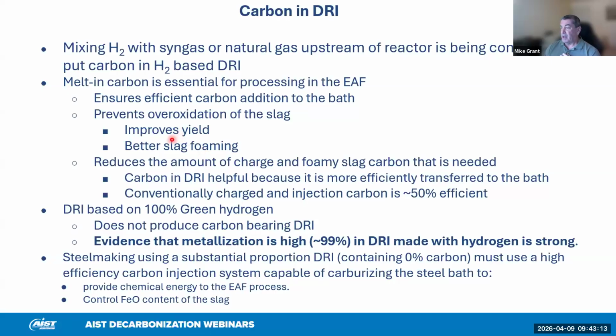The carbon, of course, improves the yield. It makes the slag foam better, and the reason for that is because essentially it diminishes the need for extra control with your carbon and oxygen balance. So in effect, if you're putting carbon in the DRI, you don't need to charge as much carbon or inject as much foamy slag carbon. Keep in mind, though, that injection carbon in traditional conventional systems is about 50% efficient. We lose about 50% in the fourth hole due to the negative pressure inside the electric arc furnace. It drags a lot of the injection carbon out, and we lose a lot of that.